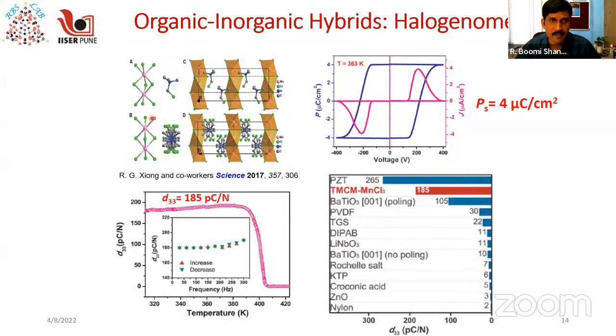This is an ammonium cation, and this is an inorganic halide chain. This is a manganese chloride chain, and this molecule exhibits a ferroelectric ordered state at room temperature, and at high temperature it exhibits a paraelectric state, which means that the polarization becomes linear at certain higher temperatures. So this material exhibits a very good ferroelectric polarization.